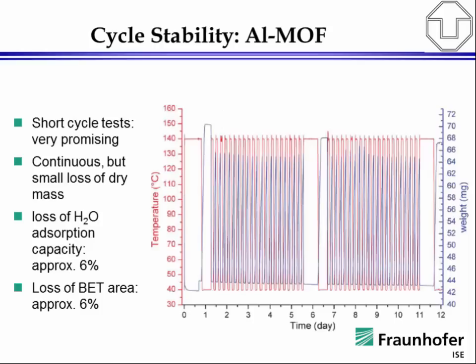and the next slide shows the durability test typically carried out by Fraunhofer ISE. And here the research shows that aluminum-based MOFs have a very good durability. There is still some loss of BET surface area, some loss of uptake in cycling, but the example shows that it is not hopeless, and the benefit is really the high capacity and the tunability of the water uptake that MOFs can provide. So these both were two examples where we think the future research in the energy storage has to be focused further, energy storage of carrier gases and energy storage in terms of heat storage.